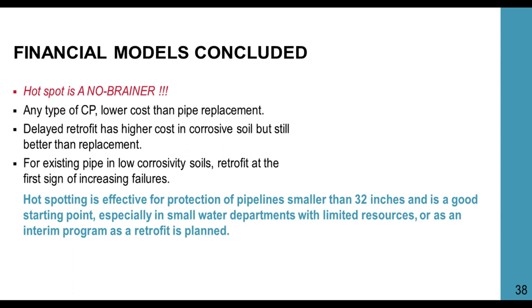So what was the conclusion from our financial models? The financial models concluded that hot spotting is a no-brainer. Any type of CP will result in a lower cost than pipe replacement. A delayed retrofit has higher cost in corrosive soil, but is still better than the replacement. For existing pipe in low corrosivity soil, retrofit at the first sign of increasing failures.